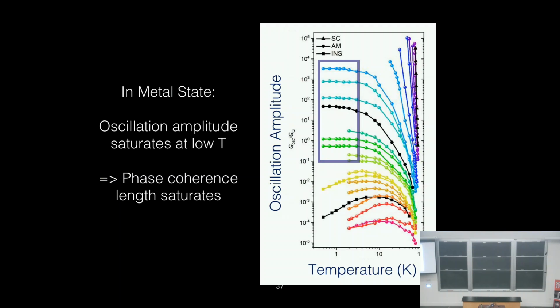Now, these quantum oscillations occur because the magnetic field is affecting the phase of the bosonic wave function, right? So there's some coherence, but it's not long-range coherence. It's local coherence. If it were long-range, we'd have a superconductor. What was interesting to see is if you measured the oscillation amplitude of these films as a function of temperature for the metallic states, there is phase coherence that grows, but then it stops growing. So it seems like there's a saturation in the phase coherence in the system. We don't know what's causing it. We would like to know.